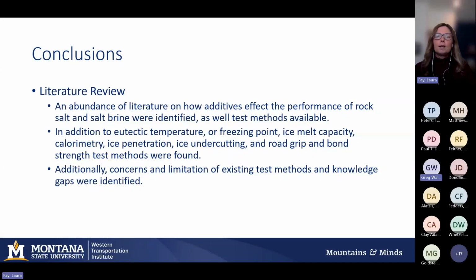So, and then there was also a good bit of information on concerns and limitations existing with the current test methods. And we ran into that with the rocker test not being validated yet for solid products. But this applies to some of the other tests as well. For example, ice penetration and ice undercutting tests also have very high error rates in addition to the other ice melting tests through the SHRP procedure.